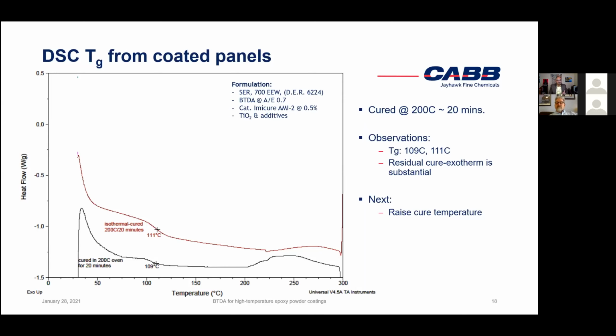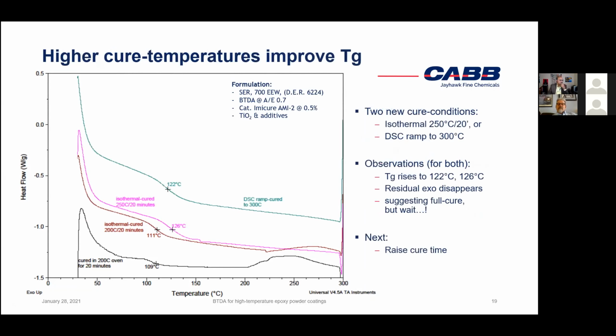Then we wanted to see what happens if we raise the cure temperature. Now we did that 2 different ways. In one case, we just did 20 minutes isothermal in DSC cure, but instead of 200 C, we did it at 250 C. So there is really no difference except the 50 degrees C bump. And then another experiment we did where we took the uncured powder and just continuously heated all the way to 300 Celsius. So basically ramp cured in the DSC. And let's see what we got for the 2 curves that way. So when we did the isothermal, same kind of thing as the brown curve, just going up from 200 C to 250 C, the Tg we got was 126 Celsius, a nice little bump.